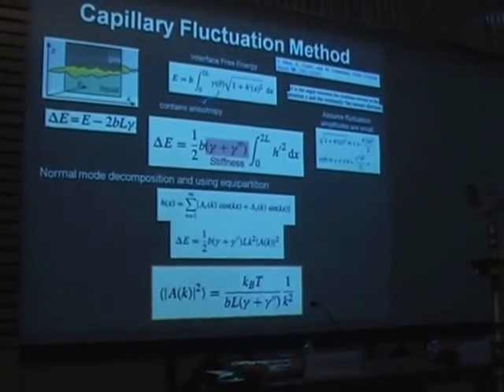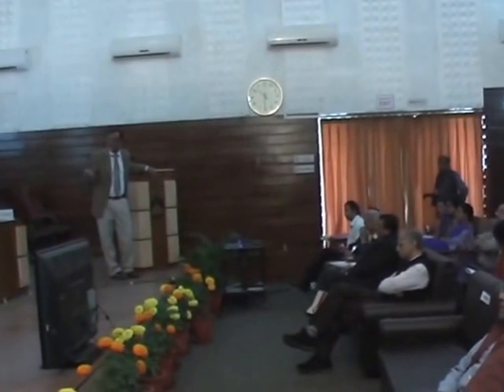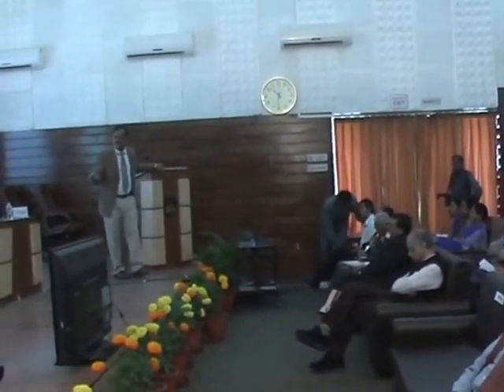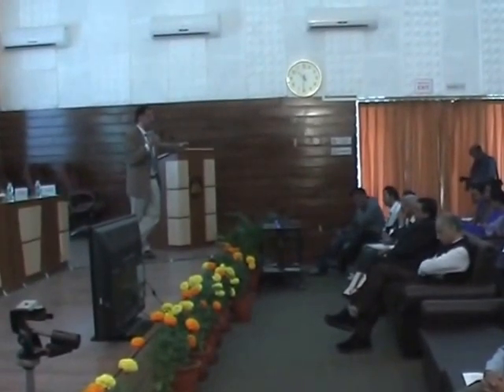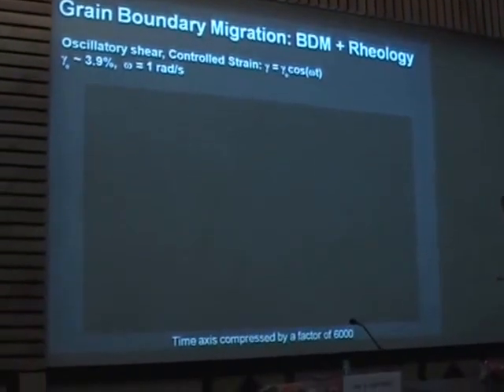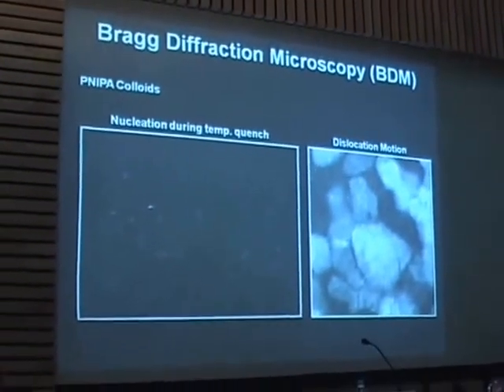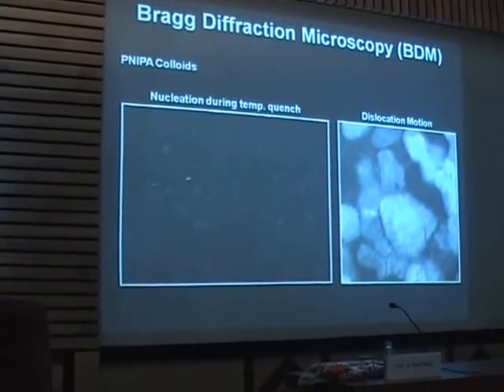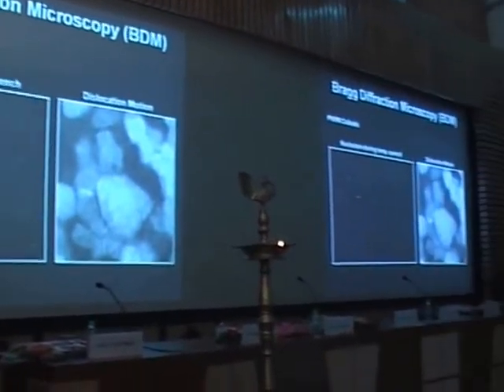We look at the capillary fluctuation, and from that fluctuation spectrum we deduce the surface stiffness. And that surface stiffness is very different for the two types of interfaces. So this is essentially the essence of this result, all this data which I will not go into. At the end of the day we show that one of the grain boundaries is very rough and mobile, the other grain boundary is not that. And this has implications on the grain growth. We can also follow the entire crystals, and we can show that some of the crystals will grow at the expense of other crystals when you shear. So this is the first time in this literature that we can see a direct anisotropic growth of the crystals under shear, which has some interesting physics.